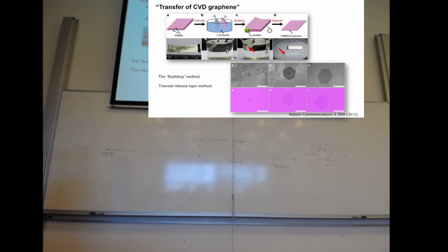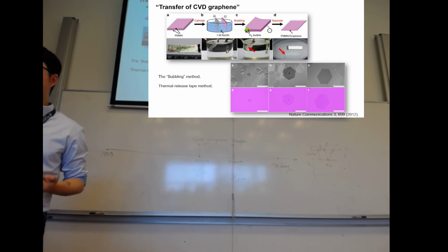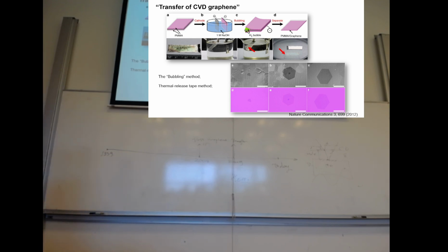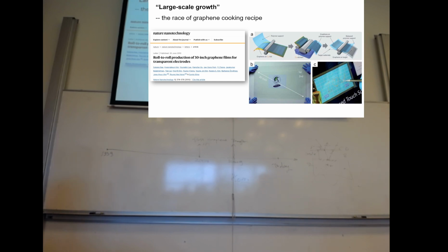And now people found that if you use a different way of chemical vapor deposition, for example, plasma enhanced, you can actually deposit graphene directly on top of silicon oxide. That's another story, but at that time people were using this kind of transfer technique.